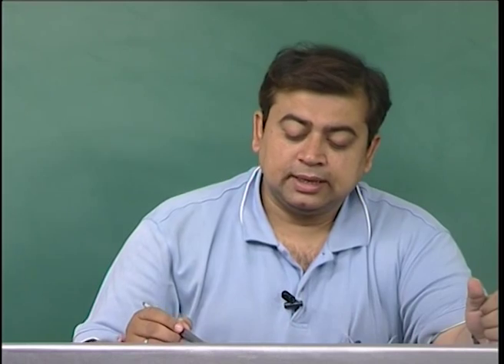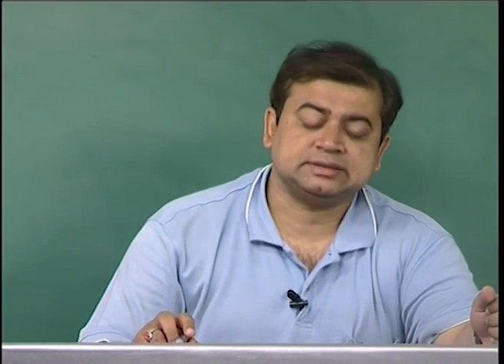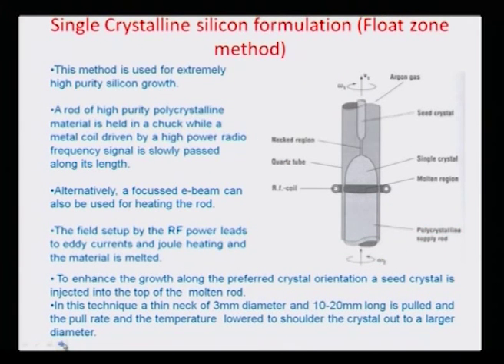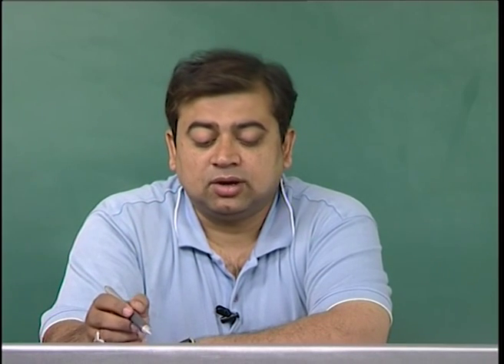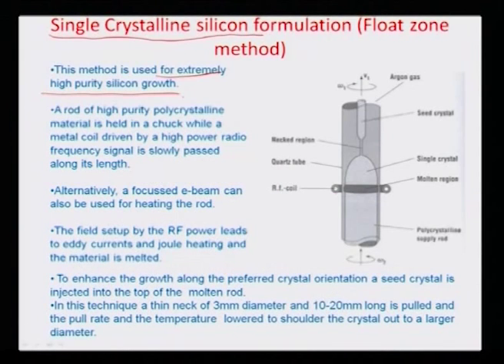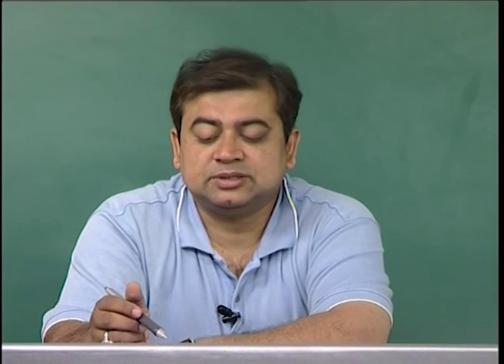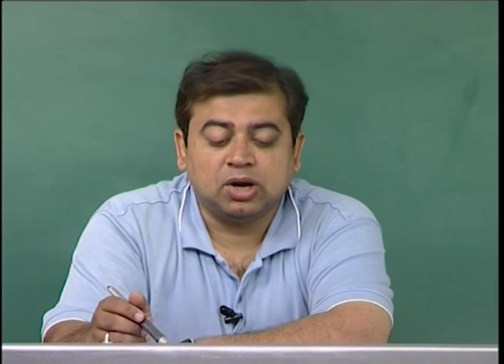Okay. So the other method, which is of some prominence, is called the float zone method, which is another very important method for realizing single crystalline silicon. This method is used for extremely high purity silicon growth, although the downside of this process is that you cannot go above a certain diameter of wafer. Like in Czochralski, you could go up to any extent, including 8 inches or 5 inches. Bigger size wafers are also possible. In this particular case, it is only limited to smaller size wafers.